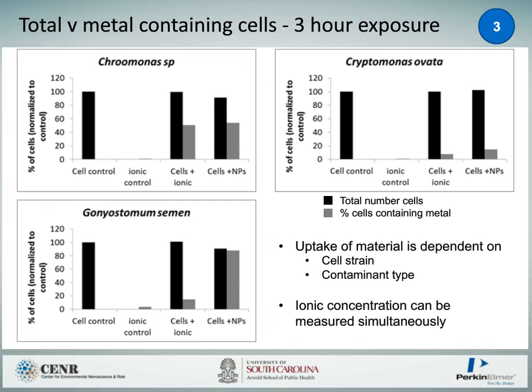So if we actually look at some results, the things that are interesting that you can get from here, we're looking at total number of cells, which were measured by hemocytometer, in black, and then metal-containing cells, which are the grey bars. So in our 3 different species, we're getting 3 different responses. Our small algal cell, which is the Chroomonas sp, we can see that we actually counted around 100% of the cells at each point after 3 hours of exposure. So we're not really getting much cell death or cell growth in this period of time, which is what you'd kind of expect. If you look at the cell control and the ionic control, we're not getting anything coming through in terms of percentage of cells containing any metals, which is again what you'd expect. We didn't add any contaminant and we didn't have any nanoparticles.